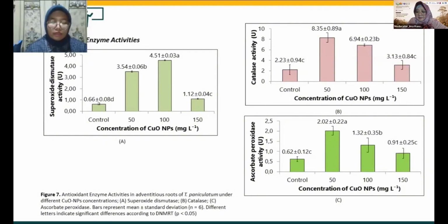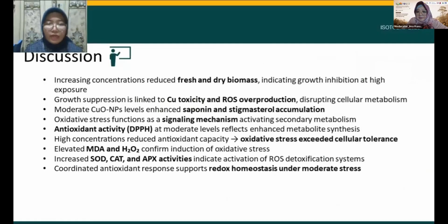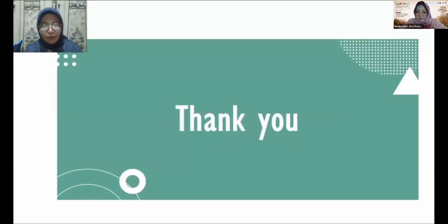Increasing concentration reduced fresh and dry biomass, indicating growth inhibition at high exposure. Growth suppression is linked to copper toxicity and ROS overproduction, decreasing cellular metabolism. Antioxidant activity at moderate levels reflects metabolic stimulation. High concentration reduces antioxidant capacity, as oxidative stress exceeds cellular tolerance. Elevated MDA and hydrogen peroxide confirm oxidative stress. Thank you for your attention.